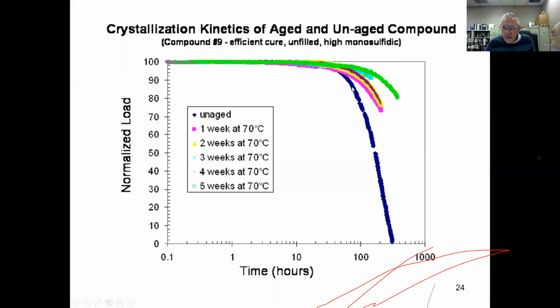And so, you know, as the sample is crystallizing, you see this loss in force measured by your force transducer. And so this is a measure of the ability of this compound to crystallize. And you can see that upon aging, after 1 week, it's crystallizing much slower than the unaged, and then two weeks, and then 3 weeks, and then four weeks, and 5 weeks.